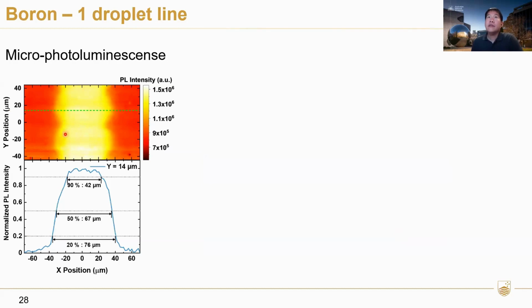So we can see with the PL image here, and when we look at the PL image, we're making an assumption that only the doped regions will provide passivation. Therefore, if we compare the PL intensity, which is a measure of the surface passivation, we can roughly identify the areas that are passivated, and therefore doped, against the areas that are not doped. But of course, this is a very indirect measurement.